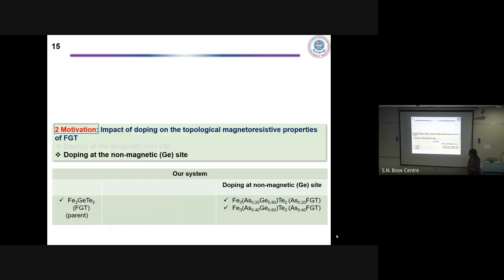And what we have observed is that... So this is the nominal composition which you started with, no? This is not the composition which you ended up with. No, I didn't end up with this one, but there was some problem with the growth. So this is based on what you start from, and more or less similar you get as a product. Oh, the composition is what I get. I didn't get your point at that time. This is the actual concentration. It's so accurate? Yes, 0.2. Like it's not 0.20, it's like 0.19 something. But yes, we could grow after repetitive trials and errors. However, I also tried growing a higher concentration of arsenic, but I was not successful in growing that.